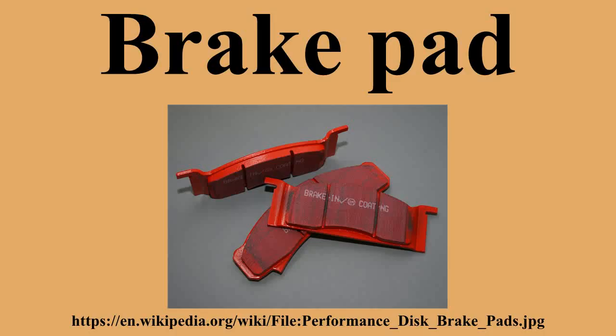For many years, straightforward asbestos was viewed as having optimal performance in all 5 categories. However, as the serious health-related hazards of asbestos became apparent, other materials had to be found. Today, brake pad materials are classified as belonging to one of 4 principal categories, as follows. Non-metallic materials. These are made from a combination of various synthetic substances bonded into a composite, principally in the form of cellulose, aramid, PAN, and sintered glass. They are gentle on rotors but produce a fair amount of dust and have a short service life.